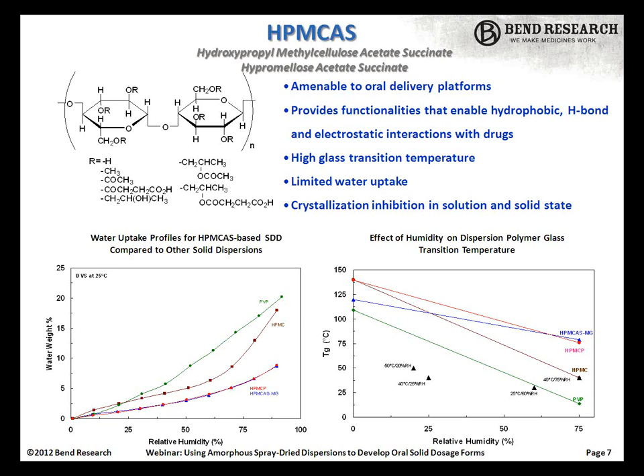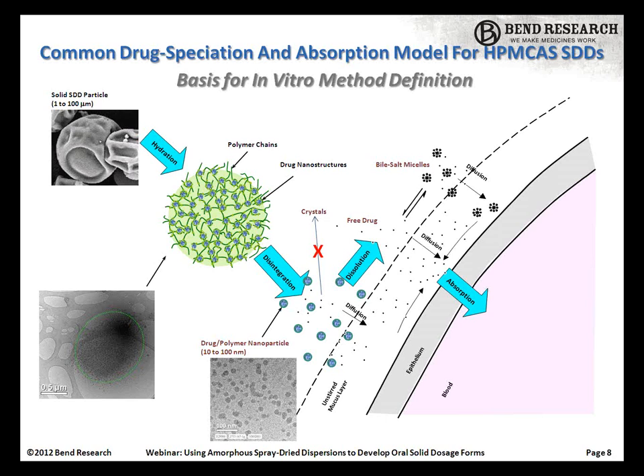Another key feature of the HPMCAS is that when it gets wet, the dispersion can speciate into a high energy form of the amorphous material, which is the key to providing the high free drug, which is, of course, the requirement and what we're looking for in order to get good absorption in the intestinal tract. So a key feature here is that the SDD rapidly disintegrates to form colloids, polymer drug colloids, and also to source the free drug.